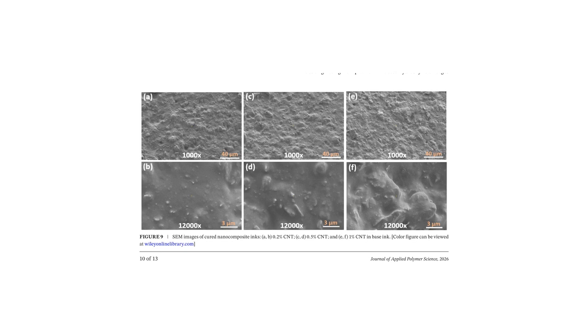The SEM images of the cured nanocomposite inks are quite revealing. They show a remarkably uniform dispersion of the fillers within the PDMS matrix. There are no visible air bubbles, large agglomerates, or other non-uniformities. At higher magnifications, the CNT particles can be seen distributed randomly throughout the matrix.